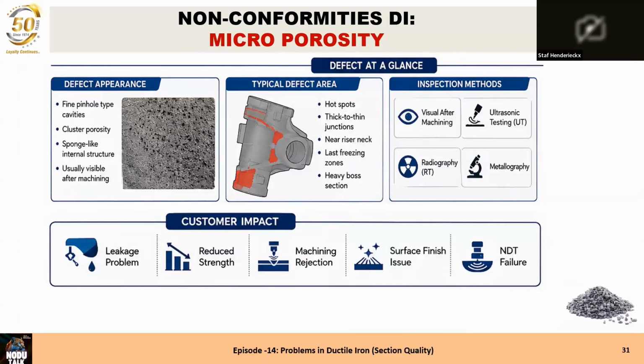So it's one of the defect appearance pictures over there. It looks a little bit like a sponge. This seems to be very, very big, but it's mostly not that big, but it's there, and it's very, very dangerous for the application, especially if you have a pressure tight casting that is pressurized during use. Where will it be? The hot spots, the thin to thick junctions, near a riser neck. Anyhow, it's at the last freezing zone, and it can be in a heavy boss section, but please, it's in the last freezing zone where it happens.